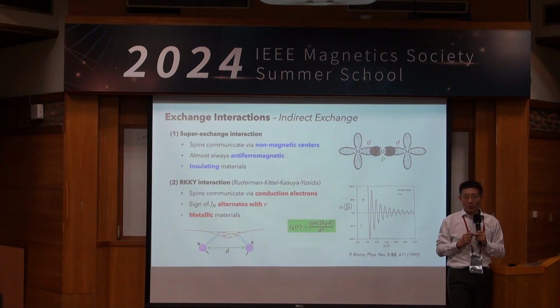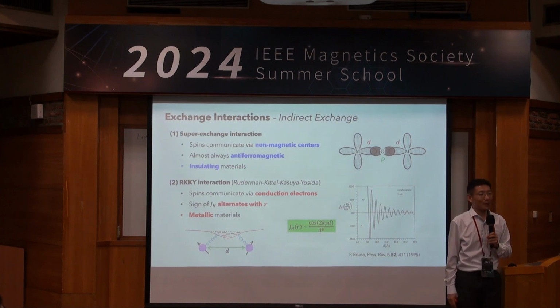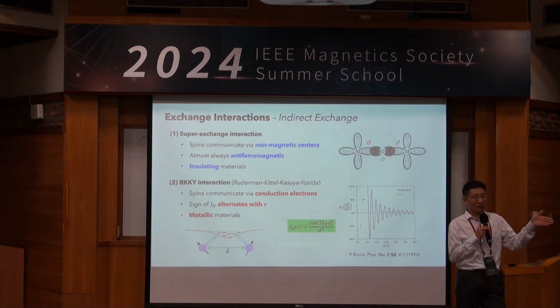But we could spend a couple of hours just trying to quantify the superexchange. A short answer is that the superexchange, microscopically, depends on the hopping energy squared divided by the on-site Coulomb repulsion. Yeah.